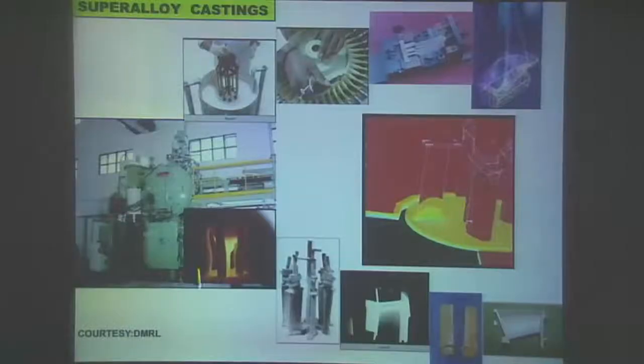So how do we make those blades? We make them by a process called directional solidification and single crystal manufacturing, which has been developed at DMRL. So you start with the CAD-CAM design of those very complicated blade contours, and your die then resembles the external shape of the blade. You put in a ceramic core to get the internal cooling, then you pour wax into this die, and you end up with something which looks like this.